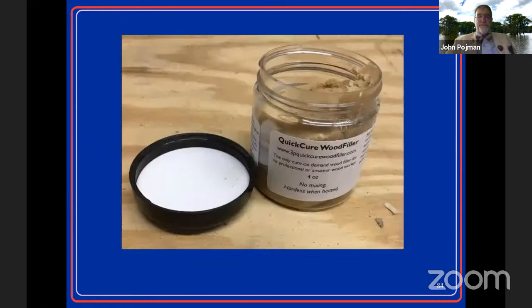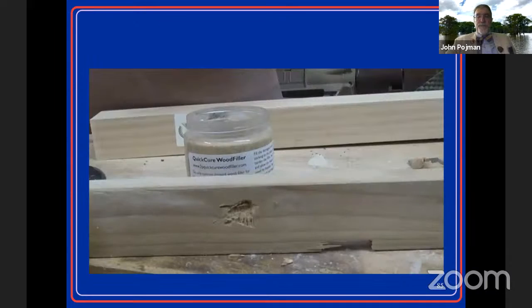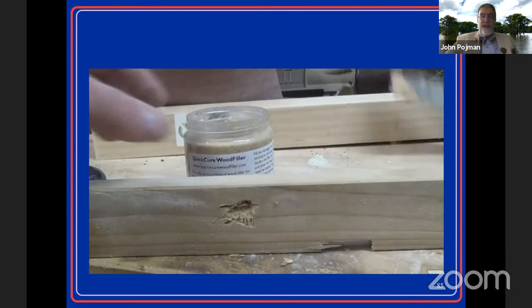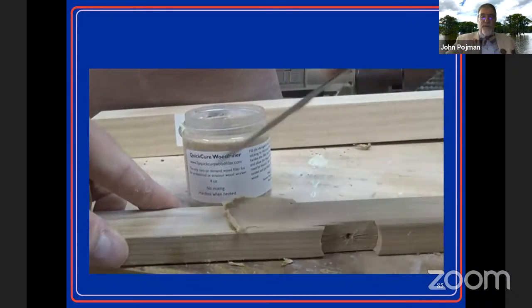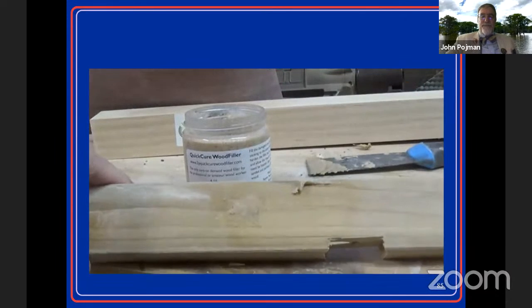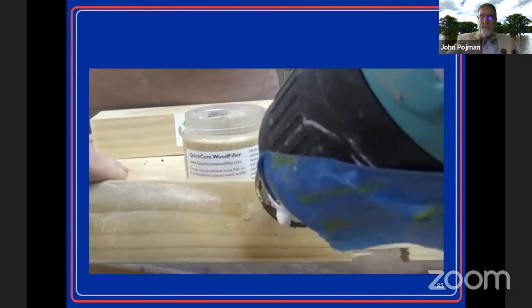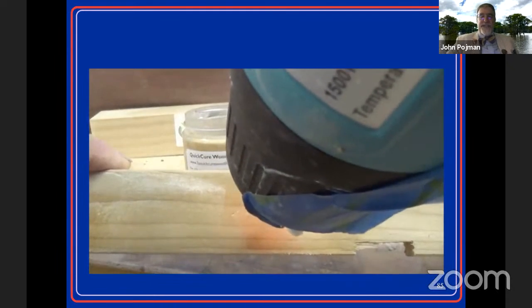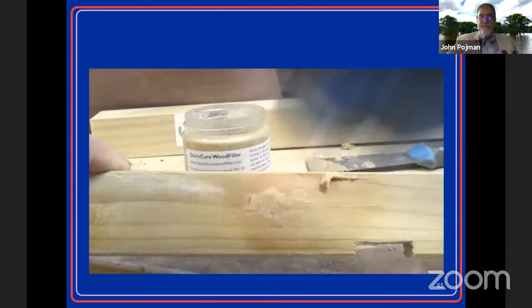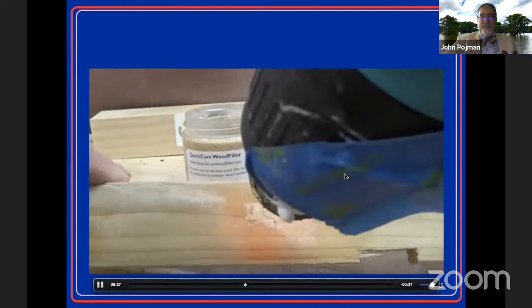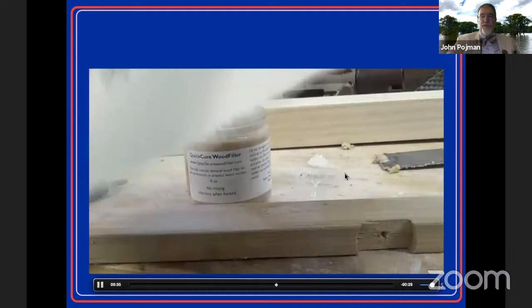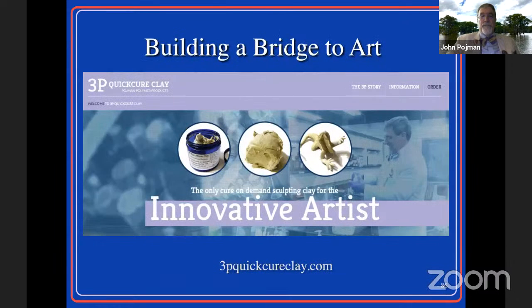And these are the products I'm selling. This is called QuickCure Wood Filler. So we've got a defect in the wood. This material will sit on the shelf for years. Open it, apply it, heat it with a heat gun to about 100 degrees centigrade, and you can watch the reaction. Now it's done. You can sand it, paint it, stain it. So you can do this repair really in under a minute. That's current materials. I'm finalizing products and then selling them myself online, and hopefully eventually get a license into a larger company.